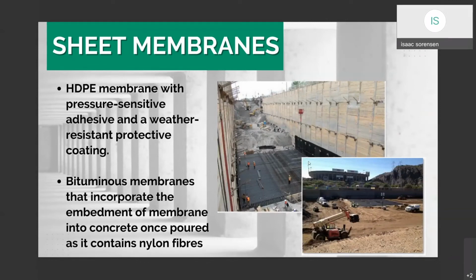Typically, in both situations, really, the adherence to the substrate itself is very important, and in order to create a situation where we don't have lateral water migration or water migrating behind the material, the substrate has to be clean and ready to receive the concrete. So on a job site where we have mud or detritus or all kinds of things just sitting on the surface of that waterproofing membrane, when we pour the concrete, if we have mud or whatever it is preventing the concrete from hitting the surface of the material, we're going to have voids in between the material and the substrate itself. So in either case, whether we have a chemical or a mechanical bond, both of them really need to be inspected before the concrete is poured, and certainly in a blindside application.